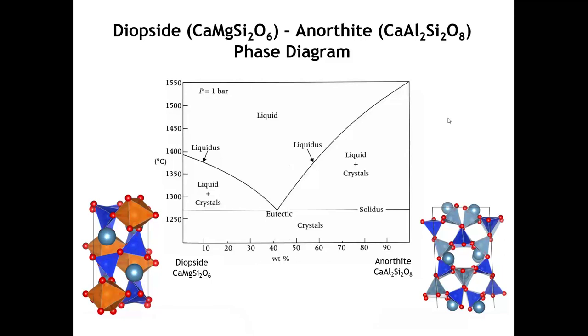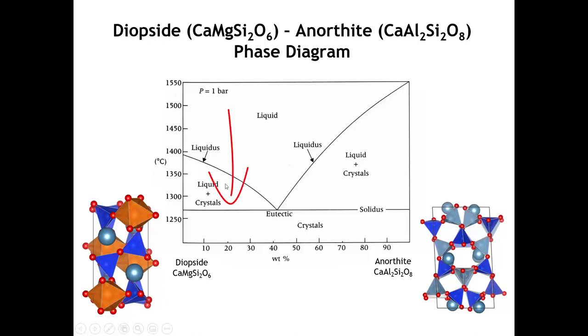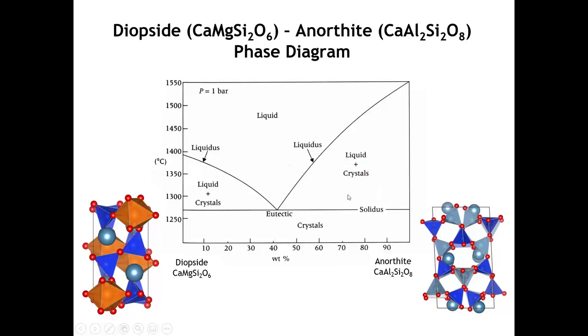Here's a real-life example of this kind of simple eutectic phase diagram, from the world of silicate minerals: diopside and anorthite, which are found in lava flows. On one side of the phase diagram, as soon as you cross the liquidus you start to crystallize out diopside, and only when you pass the solidus do you start to crystallize anorthite. On the other side, cooling from liquid initially crystallizes anorthite, and crystals of diopside form only once you cross the solidus.